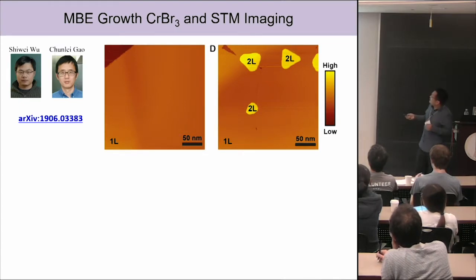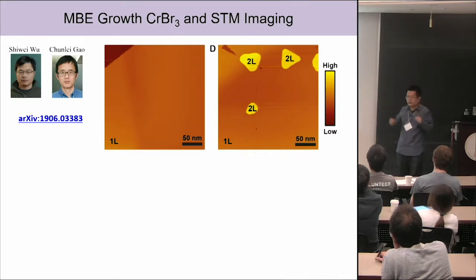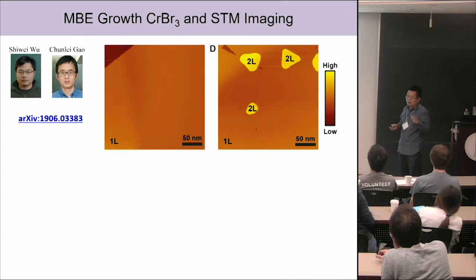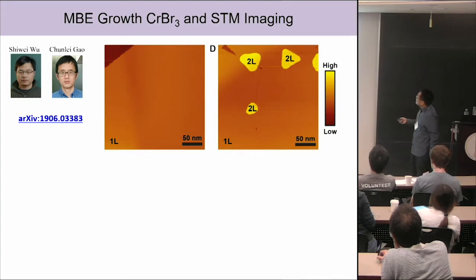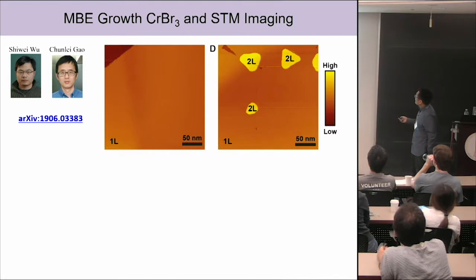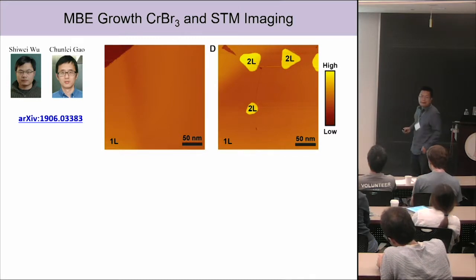Siwei and also Chunlei Gao at Fudan University looked at these problems when we discussed the physical difference between these two. What they decided to do is, we all know that all the exfoliated chromium tribromide, so far for everything we measured, and also from different groups reported, is also ferromagnetic. So what they decided to do is they actually started MBE growth. So here they show they can do MBE growth of monolayer chromium tribromide, and also with bilayer islands on top, right?